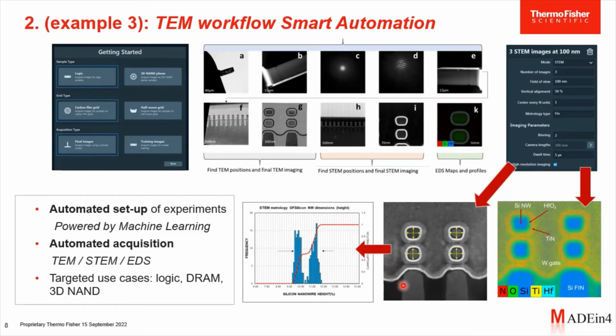For instance, in this case of the gate-all-around transistors, you can see that here there is a dimensional metrology performed using scanning electron microscopy techniques, but also energy dispersive X-ray is used to measure the composition of the layers which are around the silicon channels of the gate-all-around structures. And because we were able to generate many data, we are now also able to generate statistics, and in this case you can see that there has been a bimodal distribution of some of the relevant dimensions. And this is data which is really difficult to get in any other way.